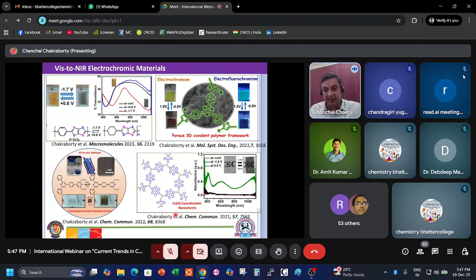So this is the NMR of this ligand, and you see the ppm values are around 7 to 9. But when it is complexed with cobalt, due to the magnetic anisotropy, it gives a very high ppm value, around 100, in this cobalt complex. We also did HRMS, high-resolution mass spectroscopy, but I am not going through that characterization part due to the time constraint.